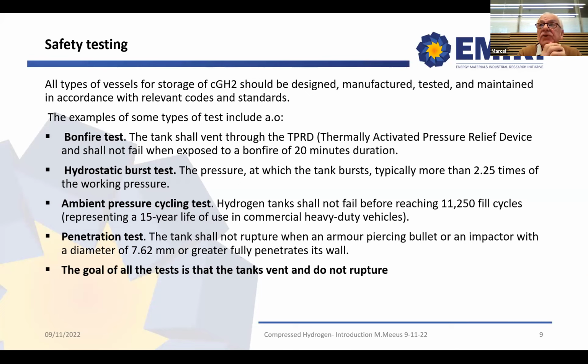There are hydrostatic burst tests done, and typically the pressure at which the tank bursts should be more than 2.25 times the working pressure. There is the ambient pressure cycling test. The tank shall not fail before reaching more than 11,000 fill cycles, and that represents roughly 15 years of use in commercial heavy-duty application. There is the famous nail test, penetration test, that should be done and safely done. And the goal of all these tests is that the tanks should vent and not rupture.